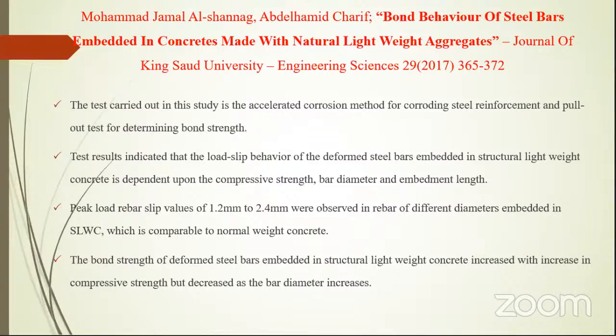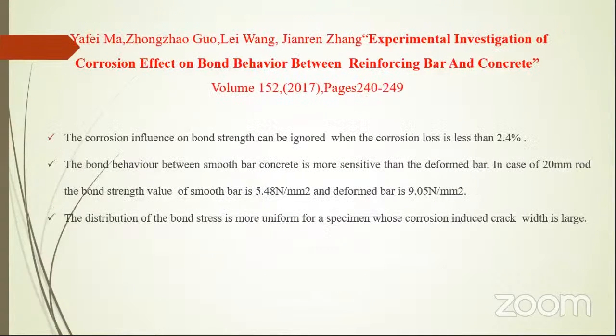The test carried out in this study used a method for corroding steel reinforcement and a pull-out test for determining bond strength. Test results indicated that the load-slip behavior of the deformed steel bars embedded in structural lightweight concrete is dependent upon compressive strength, bar diameter and embedded length. Peak load rebar slip values from 1.2 mm to 2.4 mm were observed in rebars of different diameters. The bond strength of deformed steel bars embedded in structural lightweight concrete increased with increase in compressive strength but decreases as bar diameter increases.